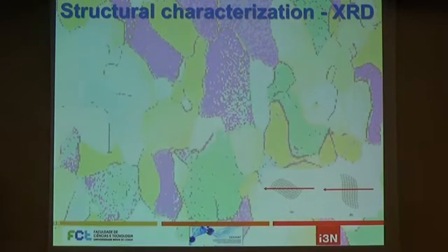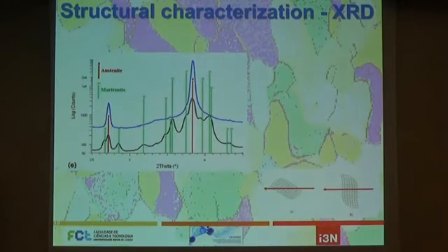And the other interesting feature you can clearly see: in the non-bent file we only see the austenite, while for the part of the file that is bent, we can clearly distinguish the presence of martensite and no clear evidence of R phase.